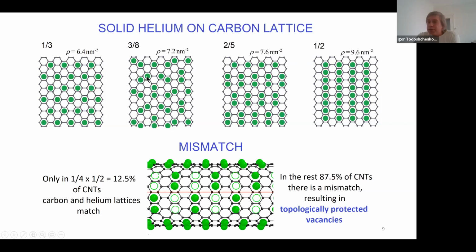These dimers come quite naturally. If you look at this 1/3 phase and you want to add more atoms and still remain in the commensurate phase, you necessarily end up with dimers. There is no other way. Now, if we look at this flake and try to form the nanotube from it, we roll it about the horizontal direction and glue, we see that generally we will have a mismatch, because the lattice period of helium is 2 in this direction and even 4, even 5 in this direction.